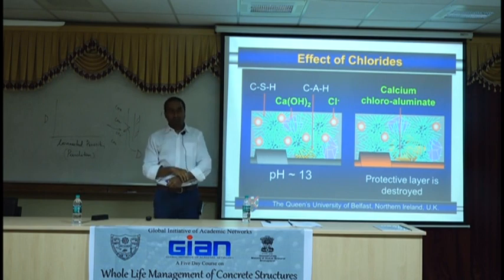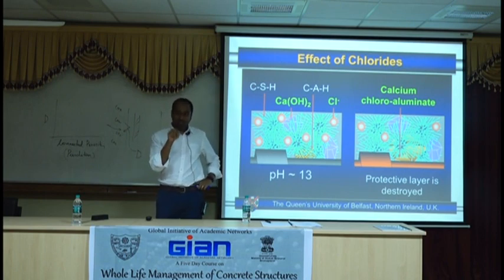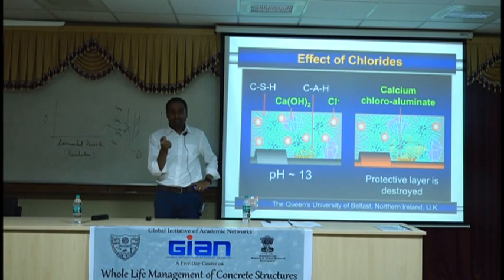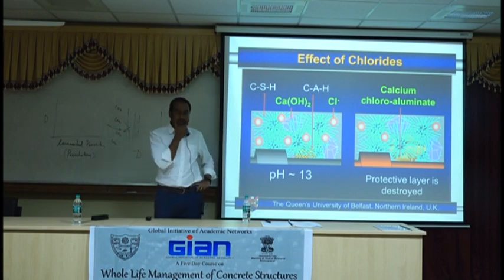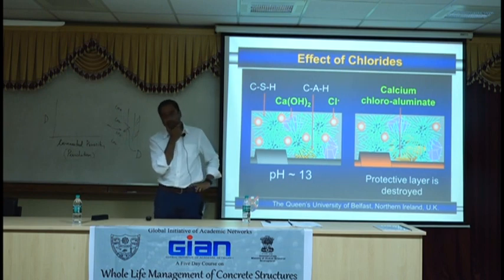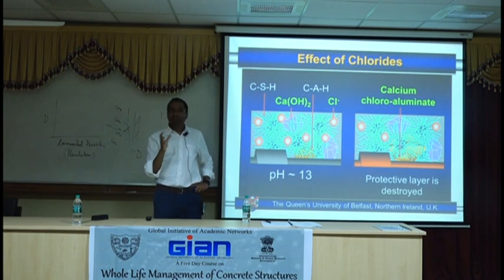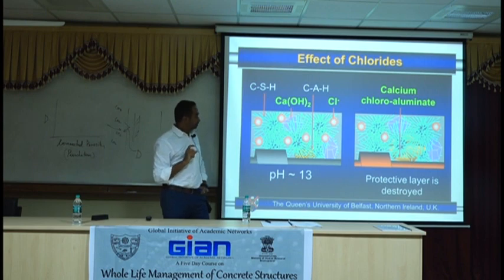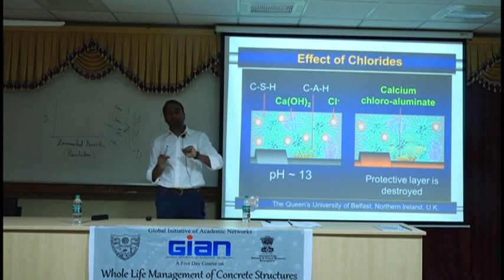But it has its own issues because I don't know the fly ash that you get here. Some fly ash are very reactive. The fly ash that we get, the coal that we get, is from Russia. They're not really that reactive. They're very dormant fly ash. So we can afford to add a lot more because you don't get that spike of reaction. But we also have the problem that the strength development will be very slow. So not ideal. You need to be really carefully planning them. But nevertheless, I like that aluminate phase.